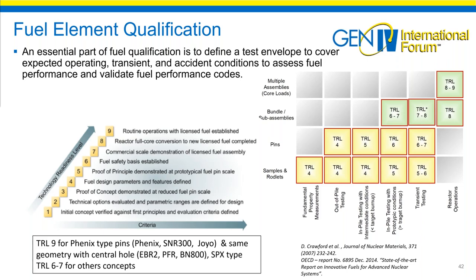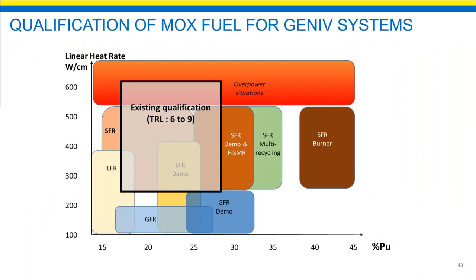So next slide, 43. This is a tentative description of MOX qualification for the different advanced systems. We put as parameters the plutonium content and the linear heat rate, but we could add the pin design and the burn-up in order to be very complete. We can just say that for compositions between 18 to 28 percent of plutonium with a conventional Phenix geometry, even with central hole or Superphenix type, the qualification was fully achieved, including at an industrial scale for the fabrication.